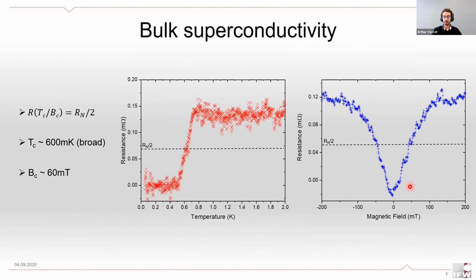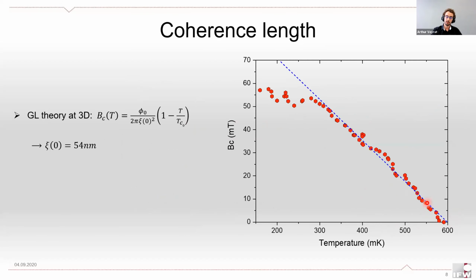If we apply a magnetic field to our sample, we also see that the zero resistance state is smoothly broken with increasing fields, and we have a critical field of about 60 millitesla when defined in the same way as previously. If we want to study the superconductivity in this sample, we can repeat this measurement, which was done at our base temperature, that is about 100 millikelvin. We can repeat it at different temperatures and look at the dependency of the critical field versus temperature. So this is the result of this study.